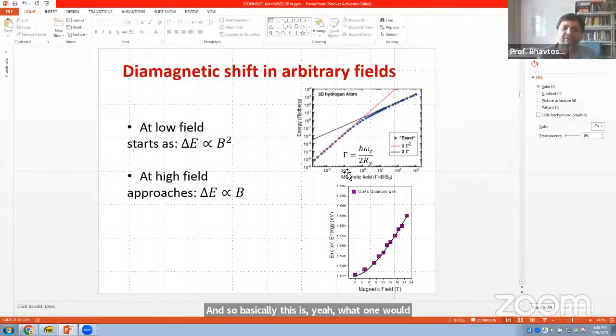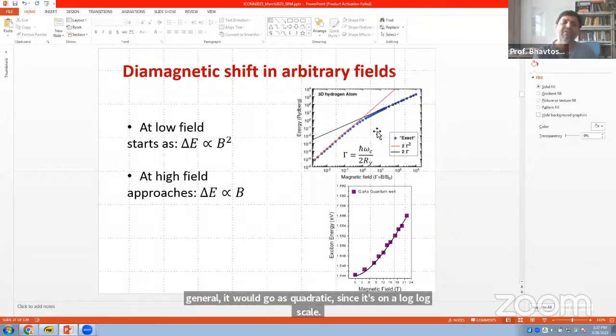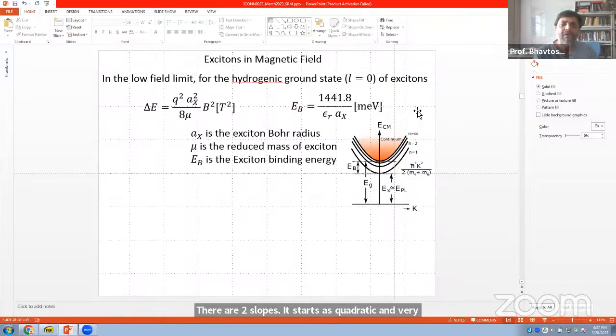The argument which I had given was only for weak fields. When you get to very, very strong fields, the effect of Coulomb confinement is negligible. Well, I should not say negligible, but essentially the Landau level effects become stronger, and that's why you get linear dependence. So if you look at the field dependence in general, it would go as quadratic. This is on a log-log scale, so there are two slopes. It starts as quadratic, and at very large fields, it tends to linear. So in the low field, you would expect the shift to go like B squared.